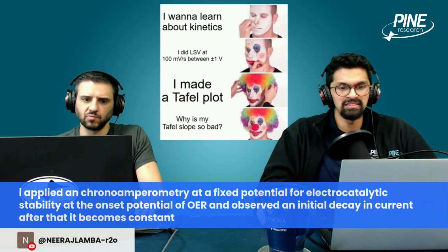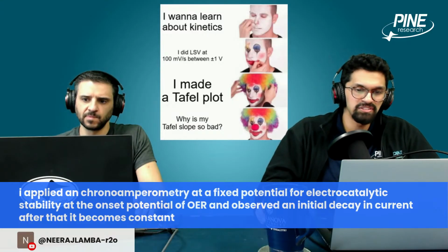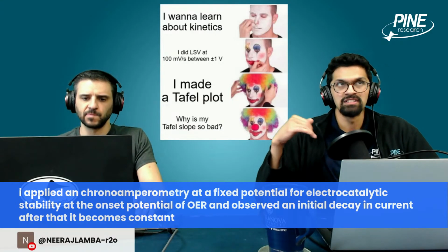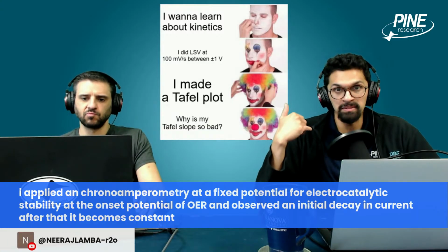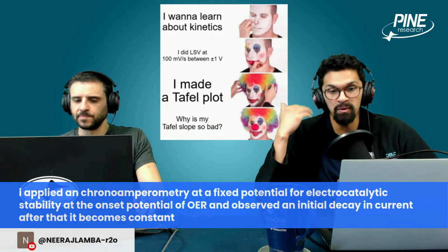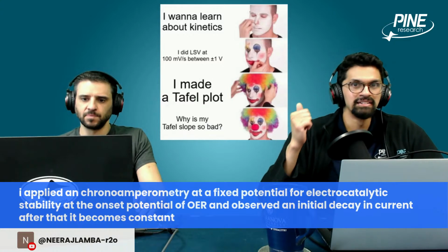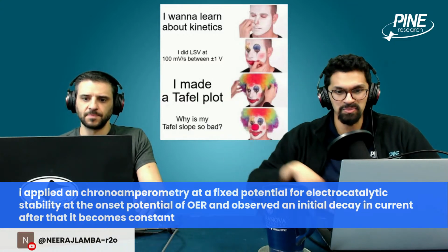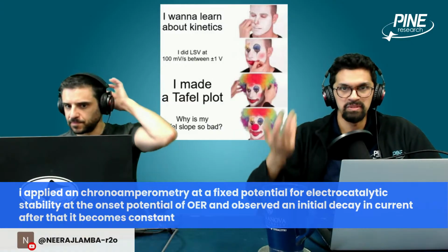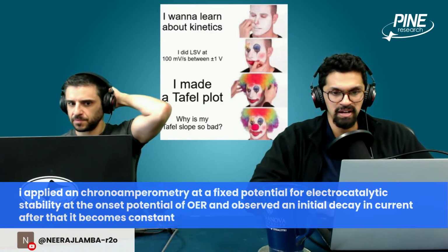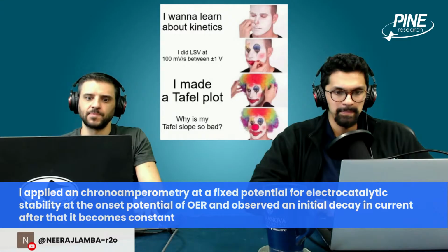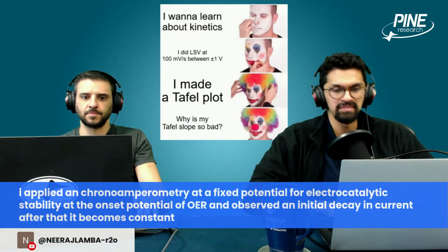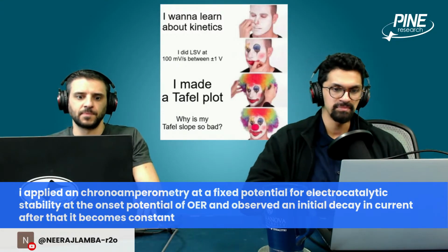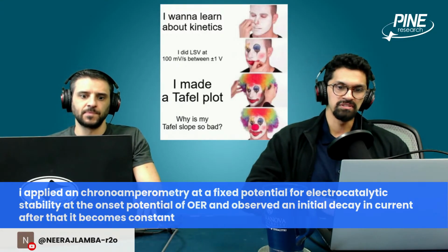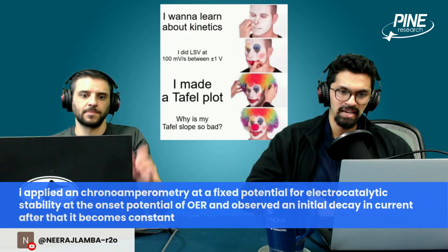And as I said, the current response usually has some kind of spike, either top or bottom, but then it decays either up or down. So when we think about decay, it's decaying this way, or maybe it's decaying up, depending on if you're doing an oxidation or reduction reaction. So I don't see any issues with that. I might also recommend, though, that when you're doing chronoamperometry, you should set the potential.